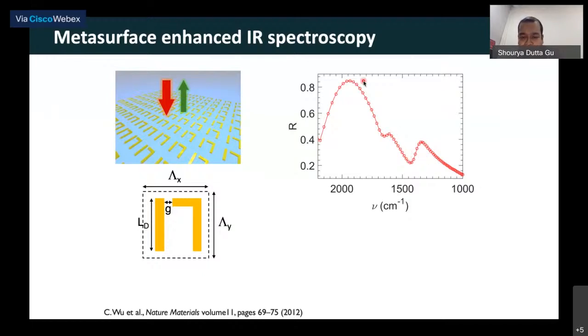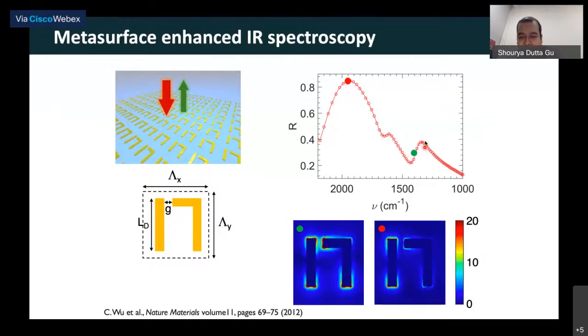So this peak here and this peak here correspond to the two plasmon resonances of my structure. Now, the way we typically say it's a plasmon resonance is by looking at the near field. So if you remember, at plasmon resonance, your field very close to the structure, or in the near field, is very significantly enhanced, right? And that is the case for both of these wavelengths, as shown here. So the field is enhanced close to this straight bar and the L-shaped bar at both these wave numbers, right?